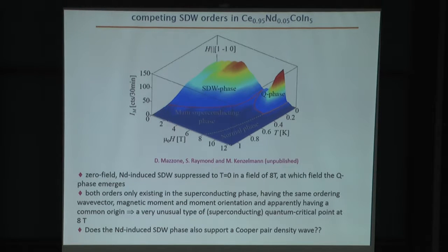What they find is that this zero-field neodymium-induced spin density wave order is suppressed by an applied magnetic field, and that spin density wave transition goes to zero temperature in a field of about 8 Tesla. And at that same field, the so-called Q phase reemerges.